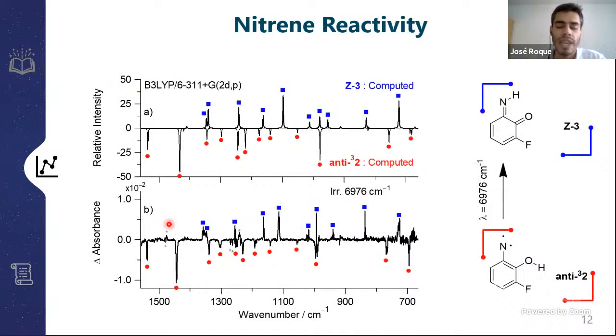So we once again tuned our laser at this frequency, and we irradiated our sample at this frequency to find out that we could indeed convert the anti triplet nitrene to the final product by excitation of its first OH stretching overtone. And here you can see the difference spectra once again. So the bands pointing downwards are bands of the reactant, the triplet anti-nitrene, and the bands pointing upwards are bands of the aminoketone. This is the experimental spectrum that we obtained, and here is the theoretical spectrum predicted based on some calculations. They match very well and leave no doubts that this reaction is indeed occurring.